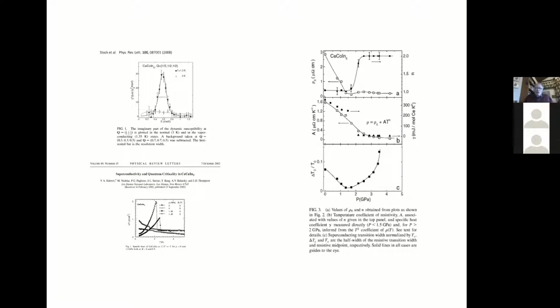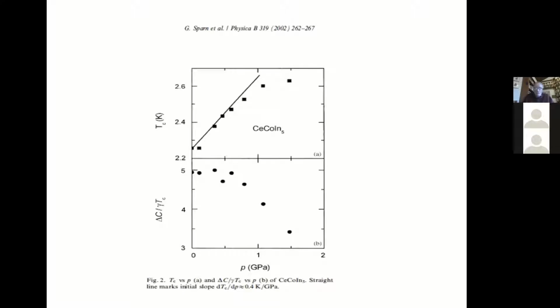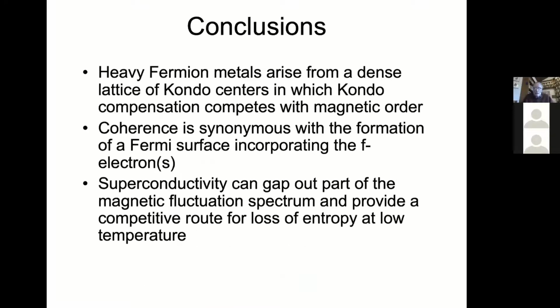Not all the electrons have been incorporated into the Fermi surface at TC. And what happens at TC in this material is that these spin fluctuations, these residual spin fluctuations, are gapped out by the superconducting transition. And this is just some more data that has to do with this. Okay, what's the conclusion here?